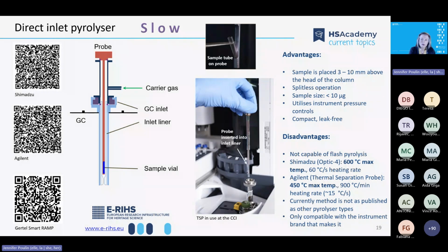For me, the most important advantage is the size of the sample. Because pyrolysis occurs inside the inlet, it can be operated in splitless mode, using just a few micrograms of sample. I've even scraped the sample from the FTIR microscope diamond cell and analyzed it using this method. So most of our samples that we get at CCI are very small. Other advantages are that it's very compact, and because it's inside the inlet, it uses the instrument's own pressure controls, and it's virtually leak-free. I haven't had a leak in 13 years I've been using it.